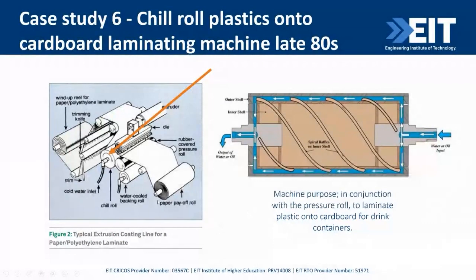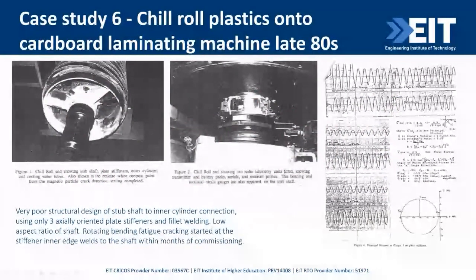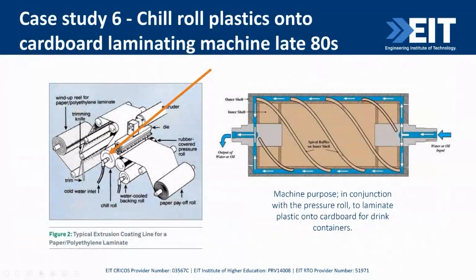Okay, this is another rotating bending case with a chill roll in a plastics laminating plant. This was imported from Europe to a Sydney plant back in the late 80s. So the chill roll is that one there, which laminates hot plastic onto the cardboard paper as it goes through, rotating, and it's compressed onto the cardboard about the chill roll with the pressure roll. So that situation of rotating and lateral loading is a high bending moment from your bearing to that stub shaft connection to the outer roll, and it's screaming rotating bending fatigue.